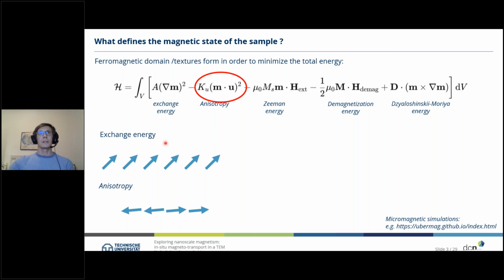If we have a system which has magnetic anisotropy, which is described here by that formula, with an anisotropy constant, the magnetization of the system, and the unit vector of the anisotropy of the system, how does that look if you have a magnetic moment configuration like that here at the bottom? I made it so that 2 magnetic moments point to the left and 2 to the right. If we minimize the energy with respect to an anisotropy pointing in a diagonal direction here, the system will end up in a state which looks like that, with the moments aligned parallel to the anisotropy axis, and depending on the starting configuration, 2 pointing down and 2 pointing up.